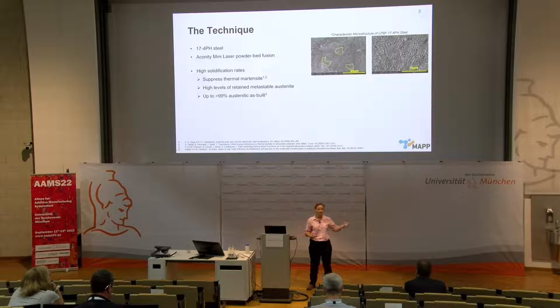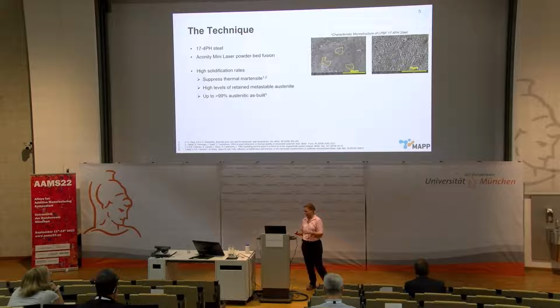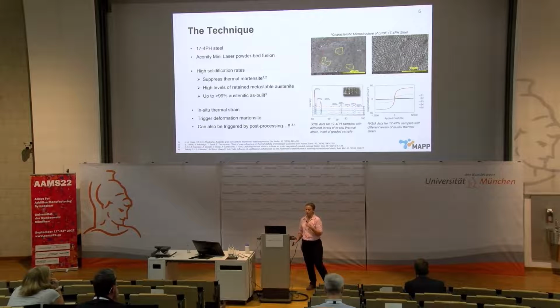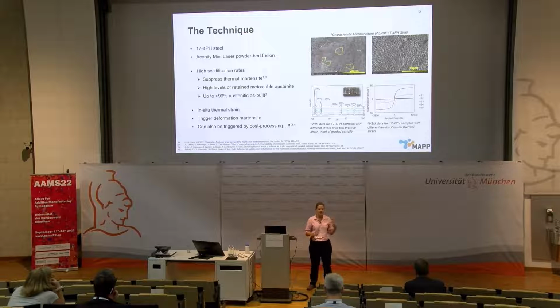You can't take 17-4 and process it conventionally and get an austenitic structure. But it also gives us something else, which is that the in-situ thermal strain that we commonly associate with additive manufacturing then triggers deformation martensite. So this is a really interesting phase transformation here. Because we can go thermally or we can go by deformation, we've got two routes for controlling how much martensite we end up with in our finished part.